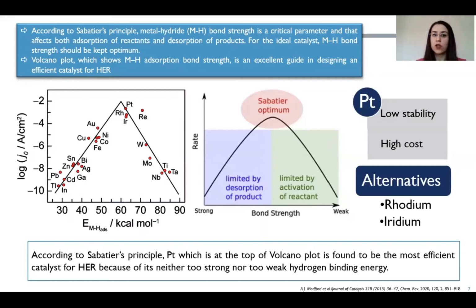both adsorption of reactants and desorption of the products. For the ideal catalysis, metal-hydrogen bond strength should be kept optimum. The volcano plot shows the metal-hydrogen adsorption bond strength, which is an excellent guide in designing an efficient catalyst for the hydrogen evolution reaction. According to Sabatier's principle, platinum is at the top of the volcano plot, and is found